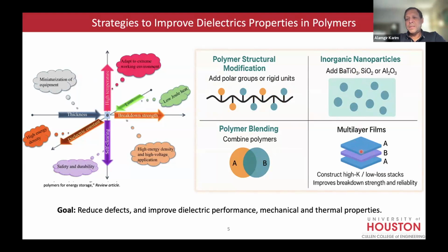I'll talk a little bit about this as well, where you can have, as I said, the interface create dielectric constant mismatch that can store energy. And I think this is actually the strategy going forward. It also resonates with the theme of multi-layer packaging and polyolefin recycling. All the Lay's potato chips bags and all that have multi-layers. Can we actually take those multi-layer films and use them as capacitors? They already have a metallic layer in them for the gas barrier properties.